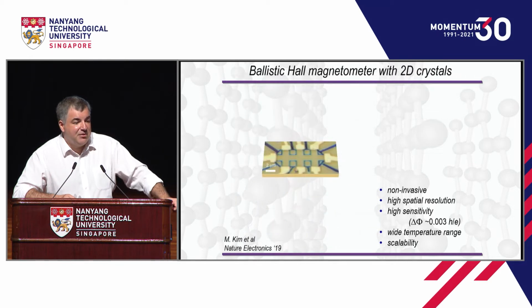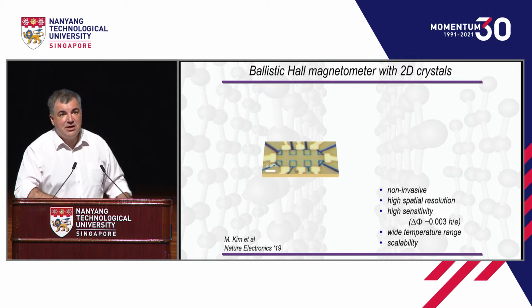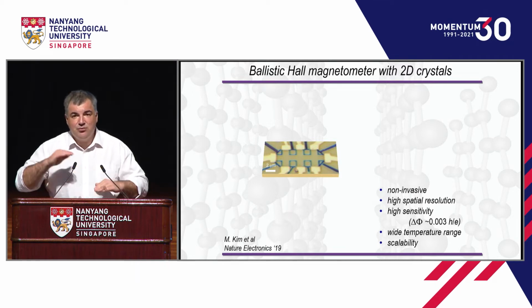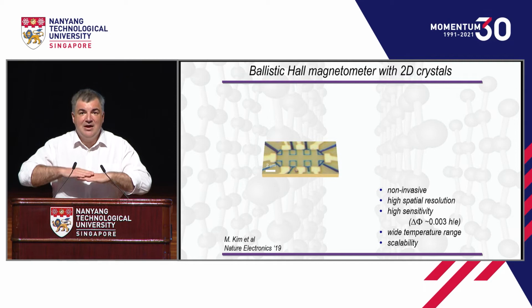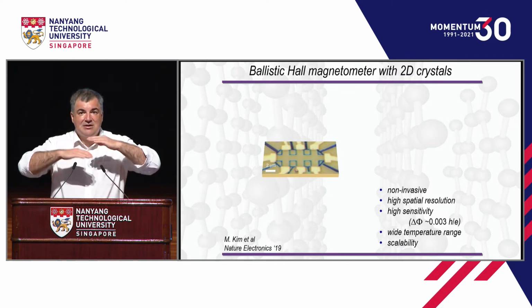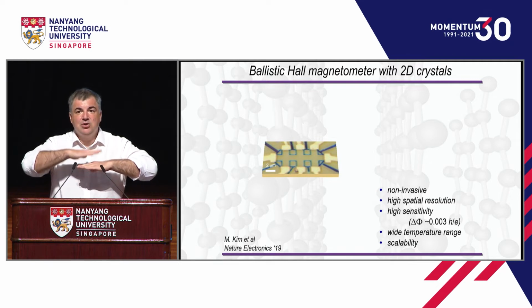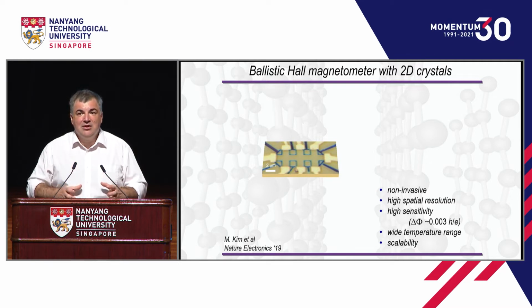And here, why we decided to study it again? Because it actually works fantastically well with those heterostructured materials which I showed you before, that we can create the Hall sensor from graphene and then stack them together and then put our two-dimensional crystal again. So the whole stack becomes your complete measurement rig. So you mix the materials and the devices together.